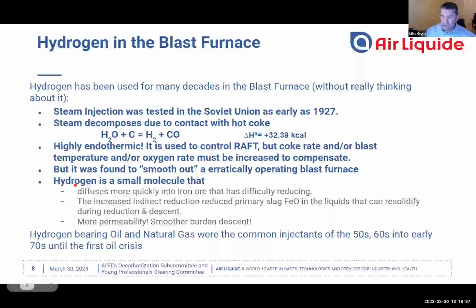And the reason for this is because hydrogen is a small molecule. It tends to diffuse more rapidly into the iron ore particles, therefore improving the reduction. And this can decrease the amount of FeO in the primary slag. FeO will leak out of an iron ore particle, touch the hot coke, get reduced, and freeze. And this has a detrimental effect on the permeability and can cause problems with burden descent. So the hydrogen helps relieve that.